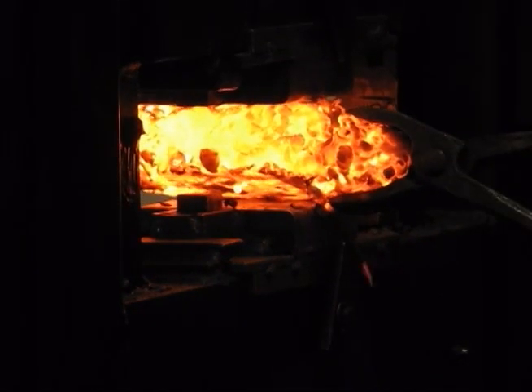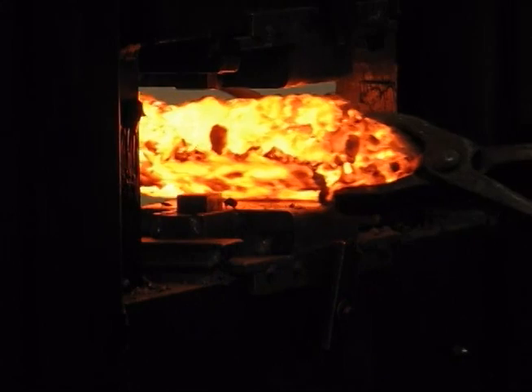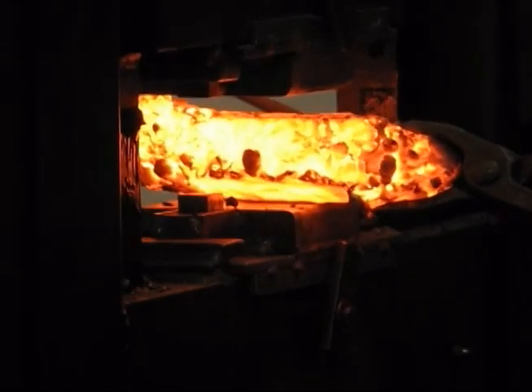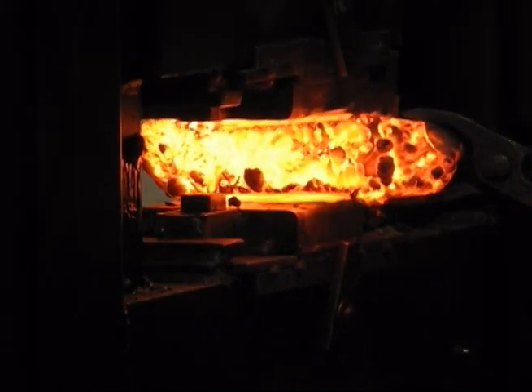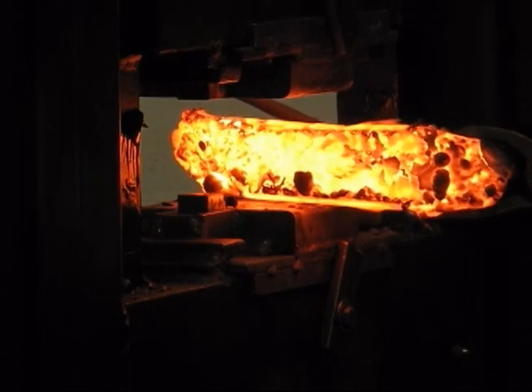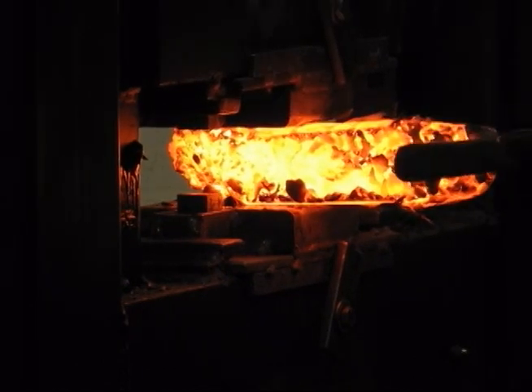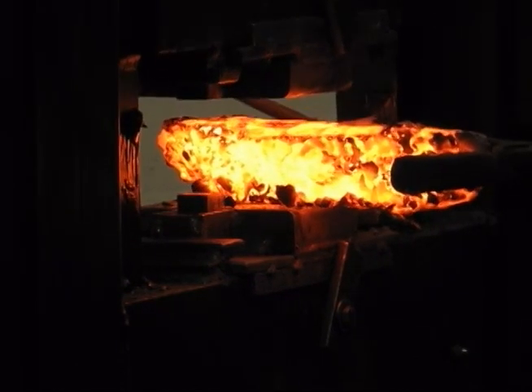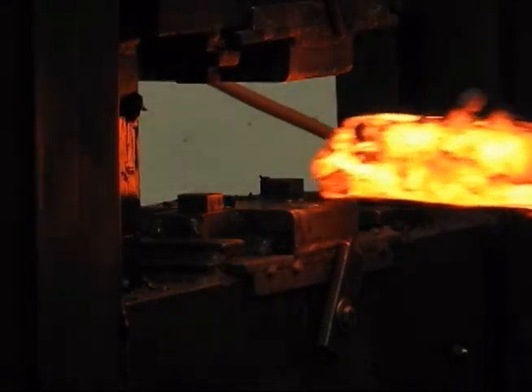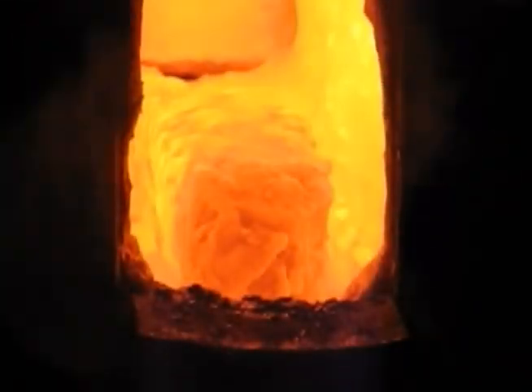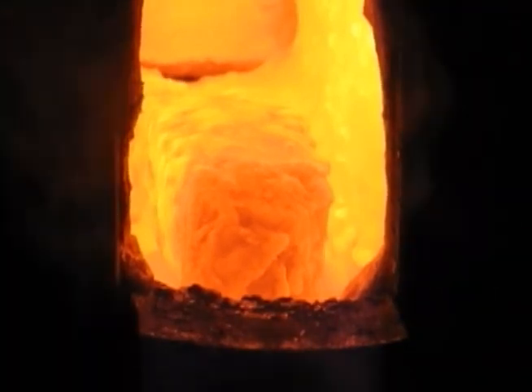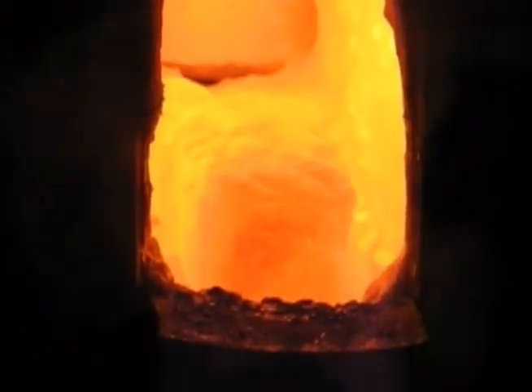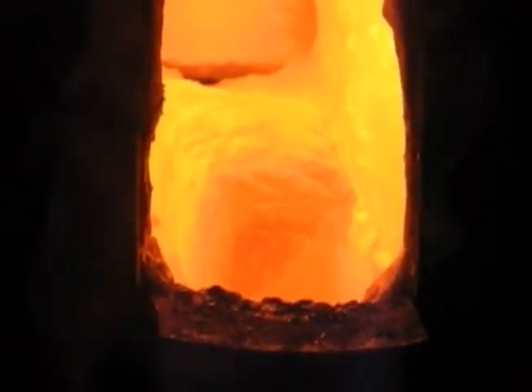Blooms are like Swiss cheese. They're full of voids that need to be closed up in order to make a solid bar of metal. There are different strategies to close up those holes and prevent air pockets that will later blister up when you least expect it. The Japanese method of flattening the bloom into plates of about a 1/4 inch thickness, which are later on stacked and welded together, is about the most effective, but also the most time-consuming way of doing this.